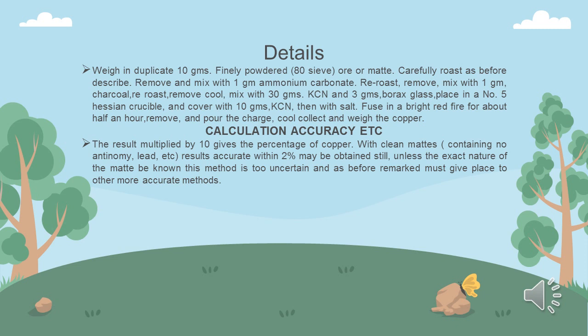place in a number 5 Hessian crucible, and cover with 10 grams KCN, then with salt. Fuse in a bright red fire for about half an hour, remove and pour the charge. Cool, collect and weigh the copper. Calculation, accuracy, etc.: the result multiplied by 10 gives the percentage of copper. With clean mattes containing no antimony, lead, etc., results accurate within 2% may be obtained, still unless the exact nature of the matte be known,